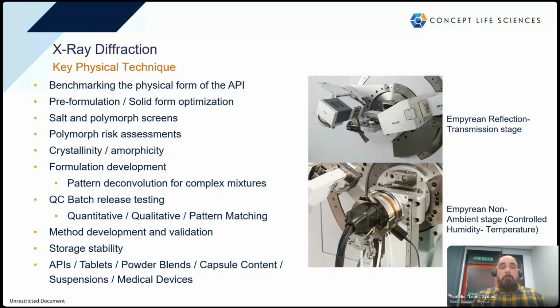but also identifying how much of one phase is within another, actually quantifying the phases if they're both crystalline or in whatever mixture within our sample. It can also be employed in later stages, like, for example, in quality control, batch release, identifying the storage stability of the API, as well as things like identifying counterfeits or characterizing medical devices.